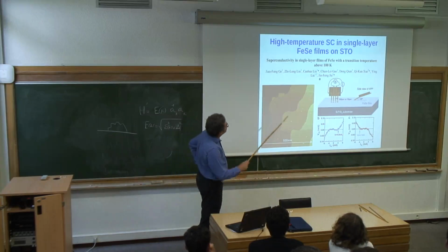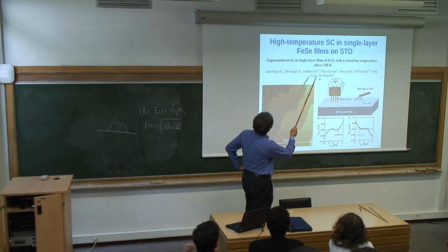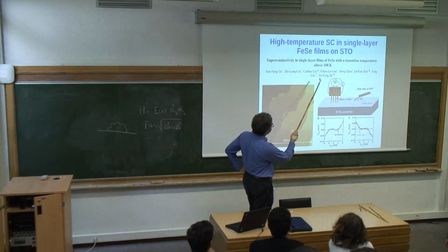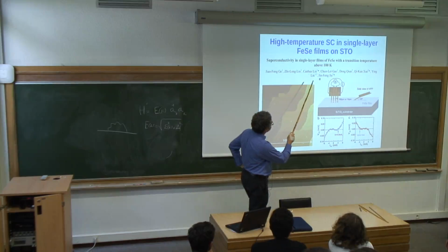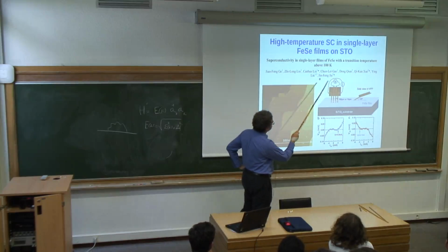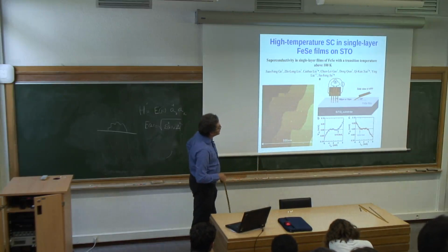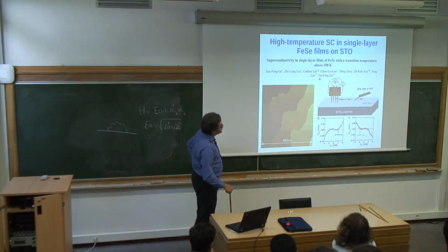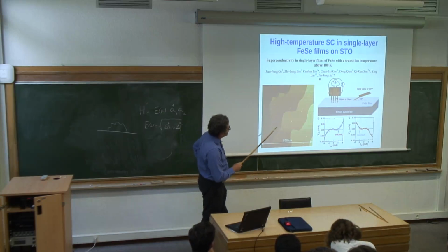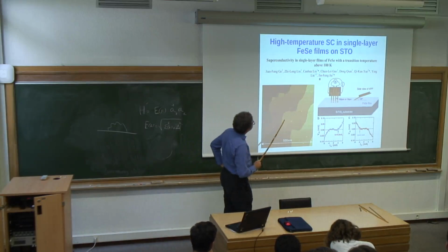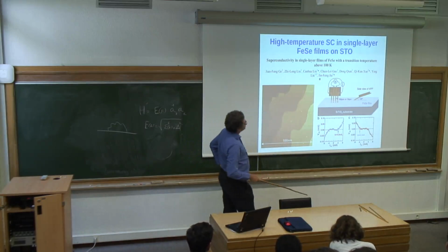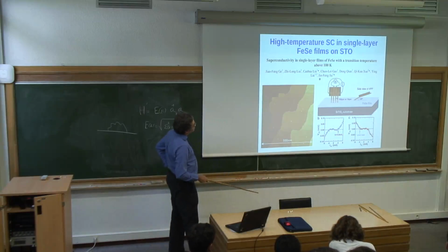So this is an experiment from Beijing, where they work on, so this is not graphene, but it's a single layer, 1 atom thick films of iron selenide. And iron selenide, bulk iron selenide is a superconductor, but TC is not anything extreme, 10, 20 Kelvin or something like that. But it turns out that if you make it a single layer film and place it on a substrate, and they used strontium titanate oxide substrate, you find that